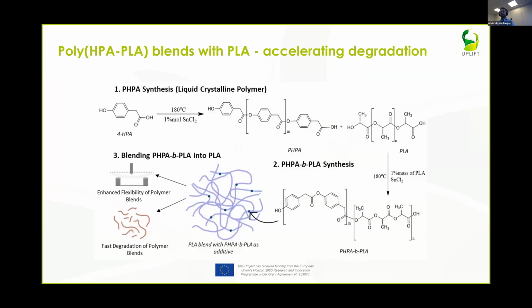If we then incorporate the synthesis of this, we can exploit the liquid crystalline behavior to do a copolymerization or transesterification with PLA, incorporating PHPA into PLA. And if we then take this and blend it into PLA, we have a possibility to obtain a range of blend compositions that actually also show a really interesting hydrolytic profile.